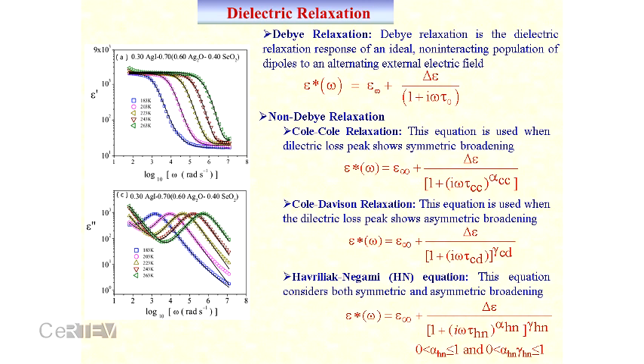And this, as I have told, is due to the electrode polarization effect, because the dielectric constant cannot change from the order of 20 to the order of 10 to the power 3. So that is why I was telling that this is our main enemy in the measurement. Here we have also shown the dielectric loss parameters. It shows a dielectric loss peak. So to describe these parameters, the dielectric relaxation in glasses, there are several functions that have been described.